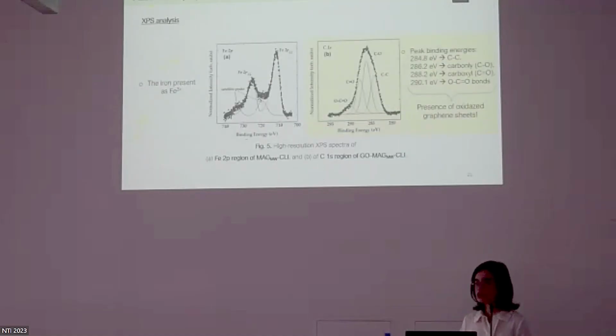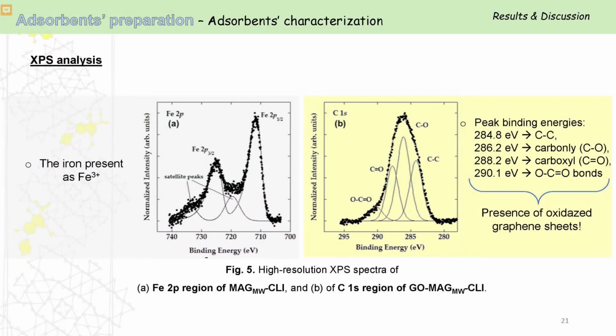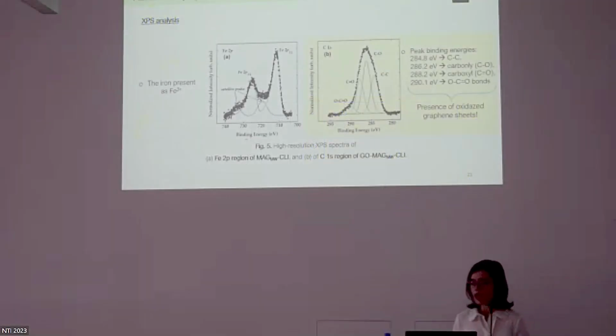The high resolution XPS analysis for the iron of magnetic clinoptilolite obtained by microwave shows that the iron is present as iron 3+, which is in accordance with the Mössbauer results. On the other hand, the deconvoluted carbon peak shows 4 peaks with binding energies listed here, which correspond to the bonds also listed here and suggest the presence of oxidized graphene sheets on the clinoptilolite surface.